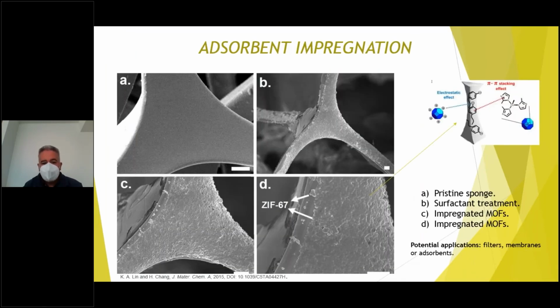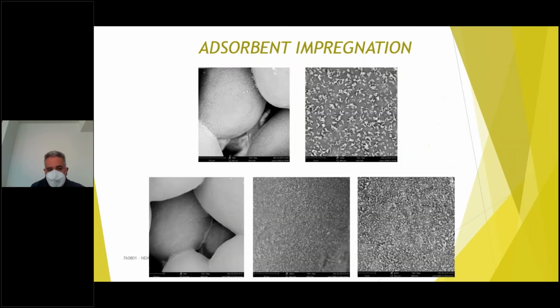In this slide, we can see different microphotographs of this process. In photograph A, we see the pristine foam, previous to the treatment. In B, we have the surfactant pre-treatment, and then in the C and D images, we can see the coating on the surface of the foam with the MOF. This is the impregnation of the MOF that we are talking about.